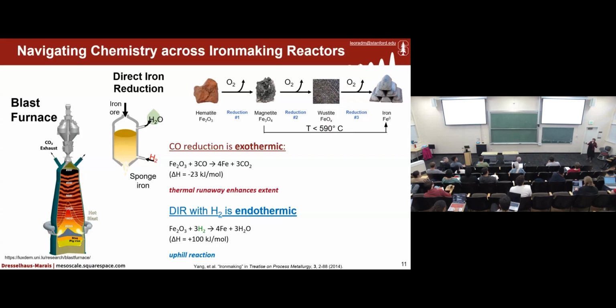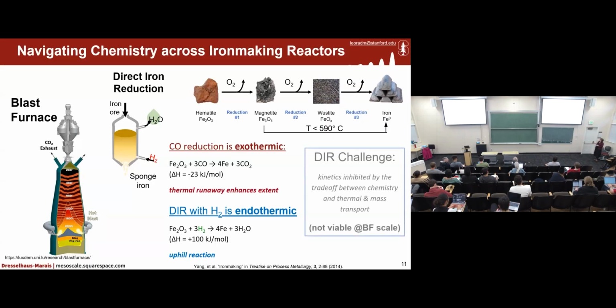So what does that mean? In our really high temperature reactor, you're basically shooting yourself in the foot every time that the reaction goes forward. So this means that now we have a much higher investment required for energy and a much more difficult reactor to design in terms of continuous flow reaction. So ultimately, this has meant that although direct iron reduction was first tried in 1954 at a pilot scale, still to this day, it is at the pilot scale, just exploring if it can actually start to have highly subsidized versions of a product that they can bring out.